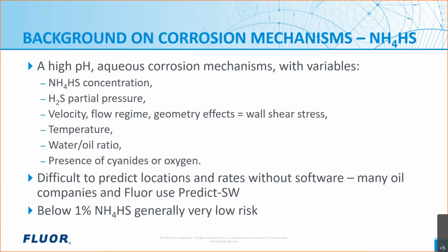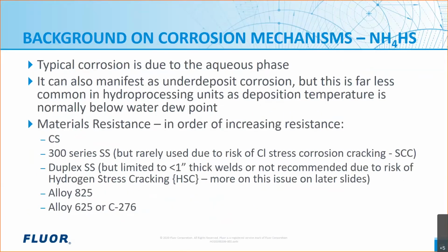One typical rule of thumb is that if you're below about 1% ammonium bisulfide concentration, generally the risk is very low. So this is a corrosion mechanism that typically occurs in the aqueous phase. Since this is a multi-phase flow with liquid hydrocarbon, hydrocarbon vapor, and water, the flow is very non-homogeneous. Things are swirling and hitting different surfaces in different manners. And often it's wherever the water is particularly swirling against the metal surface that the corrosion occurs. And the corrosion will look like a general washout. For example, one of the failures was on the outer bend of an elbow, and it blew out in such an area of thinning, maybe 10 inches long by a few inches wide, that when it ruptured, the corrosion pattern looked like a football.